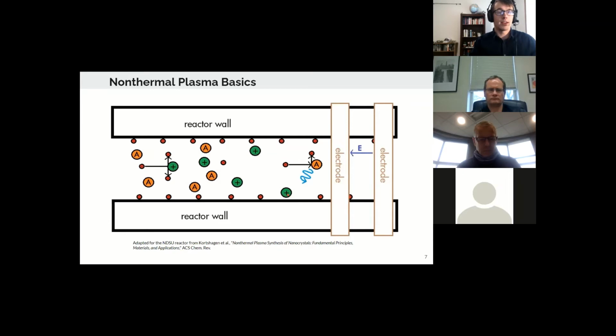There also exists an electron sheath around the plasma, which charges the large surfaces in contact with the plasma, and it charges them negatively with electrons. Things like the reactor walls and the nanocrystals are negatively charged. We chose a low pressure plasma for the NDSU reactor, but this thesis investigates the low end of intermediary pressure